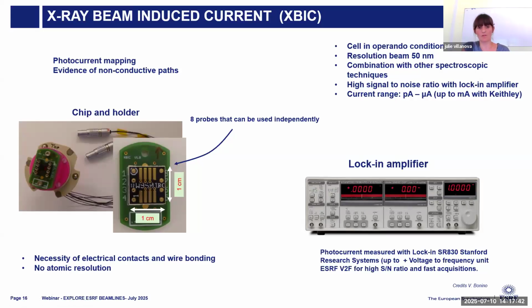But it means that before the experiments, it's important to mount the sample in a way that is compatible with this, and also prepare this very thin electrical contact and wire bonding. The advantages of this kind of measurement are that they are in operando conditions, that we have a high resolution since we scan the sample with a beam of 50 by 50 nanometers, that, as I said, we can combine with fluorescence and XEOL, and that we also have a high signal to noise ratio thanks to the use of a lock-in amplifier that is coupled with a steel chopper blade.